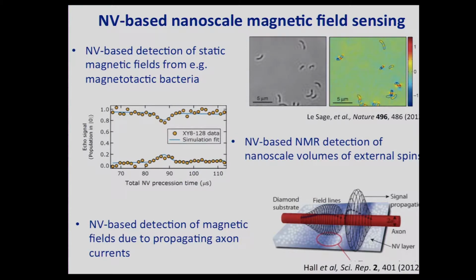I just want to point out that these experiments have mostly been done in bulk diamond. I mentioned the prospect of nanodiamonds, and that's certainly an exciting prospect. We need to work towards that. Currently, the properties of NV centers inside nanodiamonds are not quite as good as those inside bulk diamonds, just because there is so much surface. The surfaces are notoriously messy, and they have significant effects on the coherence of the NV centers.